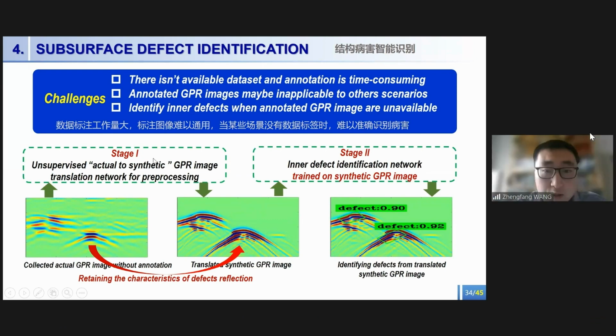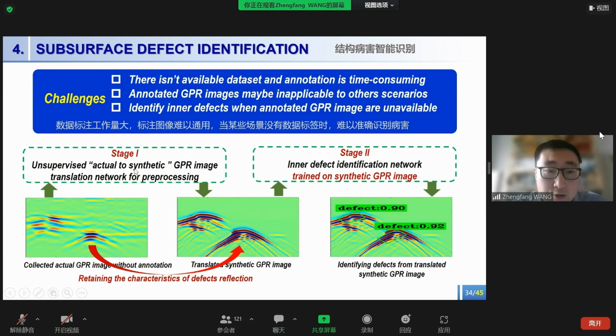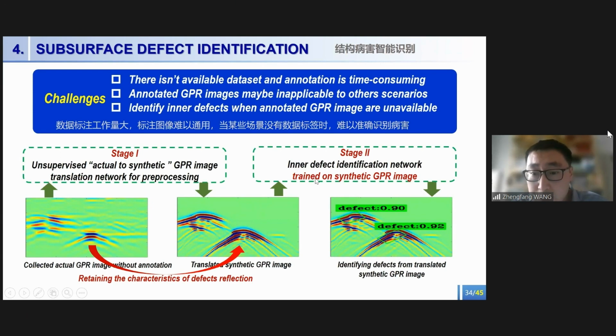So we designed a two-stage method. In the first stage, we used an unsupervised actual-to-synthetic GPR image translation network for pretreatment and generate translated synthetic GPR images. And then in the second stage, we use the DNN model, which is trained only on the synthetic GPR images, for identification.